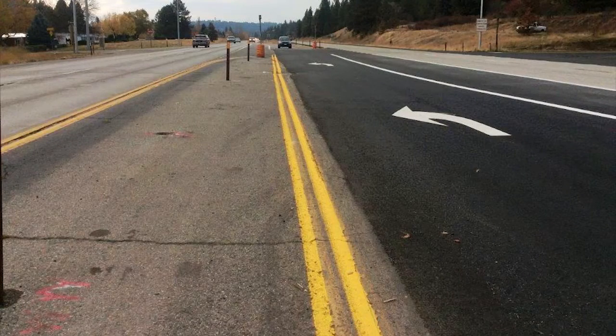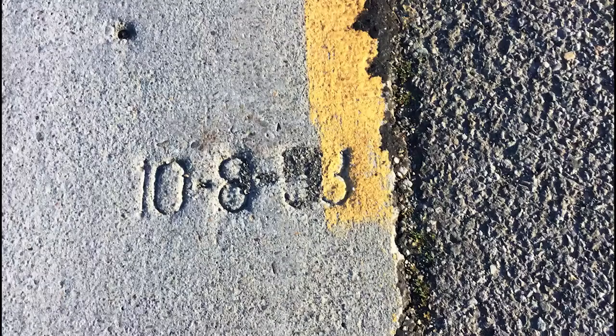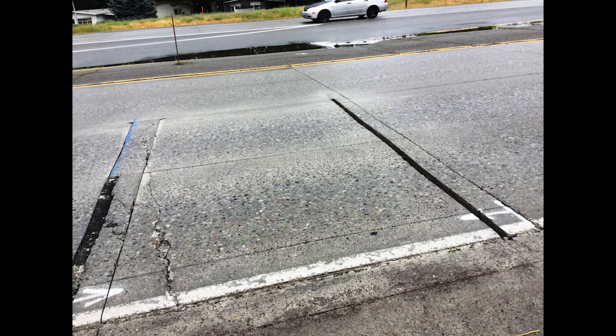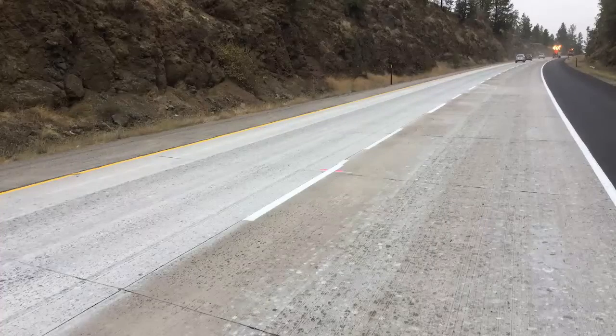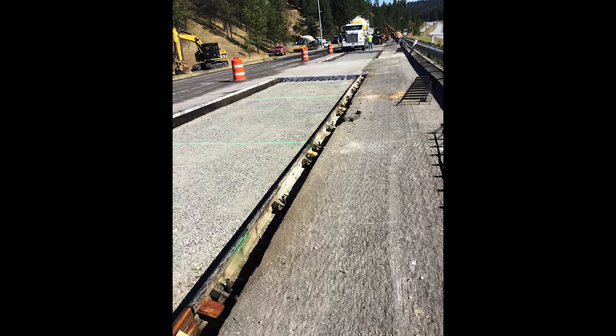Concrete pavement can be pretty straightforward, but when it needs extensive repair and rehab, it takes some coordination. US 195 is the primary highway connecting Gonzaga to WSU and was originally constructed between 1953 to 1964. The original 8-inch concrete was non-reinforced and only received a minimal amount of maintenance during its 50-plus year life. Despite the lack of maintenance, the old concrete roadway could still provide additional years of quality service. Only 12% of the panels needed replacement.